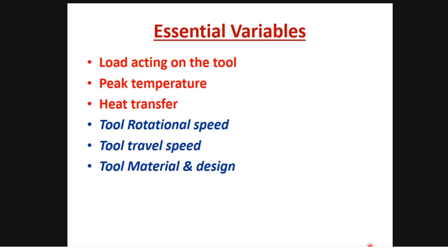So the essential variables which will affect the process are the load acting on the tool, that's very, very important here, and peak temperature and heat transfer. And then of course rotational speed, travel speed, material design, that you know. The first three points are very important as far as high melting temperature material joining is concerned. You have to consider the load acting on the tool, because tool failure is inevitable and unavoidable. The peak temperature you also have to control, and the heat transfer is also to control. So this is very important in this case.